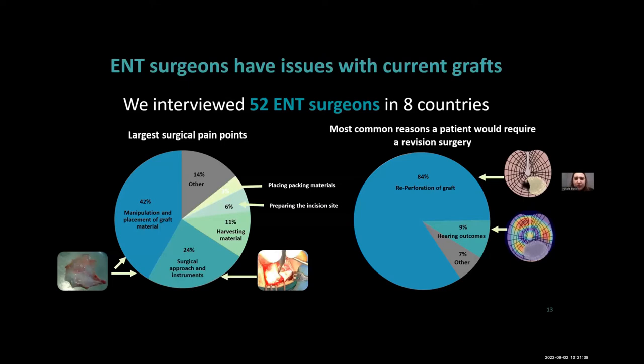And so to understand more what problems are really underlying these grafts and what problems surgeons are having with these, we interviewed 52 ear, nose, and throat surgeons in 8 countries. And we found out that one of their number one issues was with manipulation and placement of graft materials. So they usually have to harvest these materials, as I mentioned, lay them very flat and then place them, usually under a patient that has undergone anesthesia. And this procedure can take usually 1.5 to 2 hours from beginning to end because of how challenging placing these grafts is.